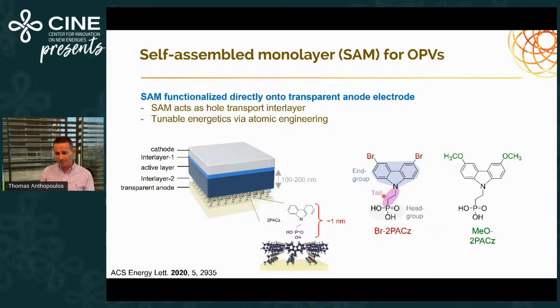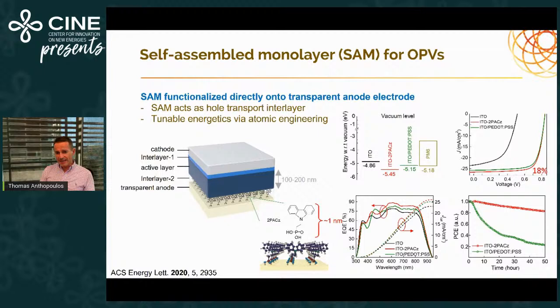We can make it longer. And the head group is actually pretty good when it comes to ITO. Phosphonic acid exhibits a very strong affinity to react with the surface of ITO. These are two different SAMs, the methoxy and the brominated versions of 2PACz, that we have also studied. We soon realized that by replacing the thick HTL, like copper thiocyanate or PEDOT:PSS, with this monolayer HTL,